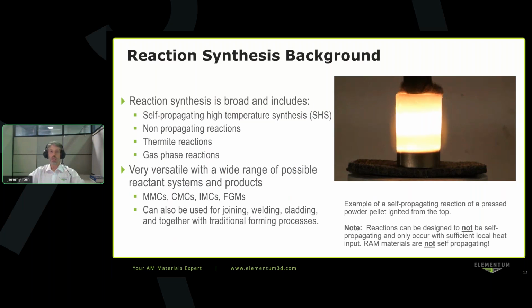So the thermodynamics behind this, I'll touch on in a little bit, but you can control this process very precisely. You can make it so it propagates in a controlled way. But in the case of reactive additive manufacturing, we're actually controlling it so that it does not propagate. Where the reaction only takes place, like in a laser powder bed fusion process, it'll only take place where the laser is actively melting the material, and it won't propagate outside of that area.